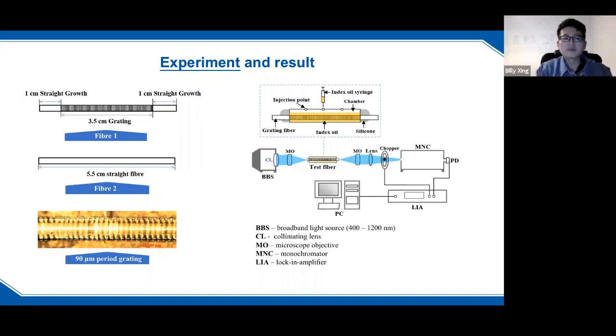So here's an experiment. We compare two fibers, one with grating, another without grating. We use a 90 micron period grating to do the experiment. As you can see, there are two fibers. One is with grating, 3.5 centimeters. Another is without grating, so a pure straight single crystal fiber. The single crystal fiber we use here is sapphire fiber. We use a index oil as cladding, because the fiber was grown with only the core, so we need to have it cladded to test the long period grating effect, to see if the light coupling into the grating is efficient and effective.